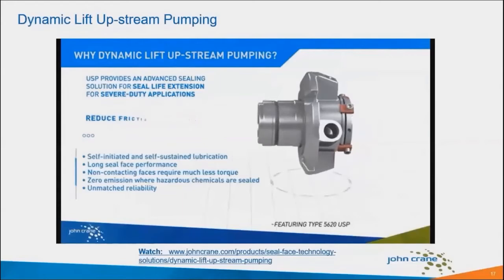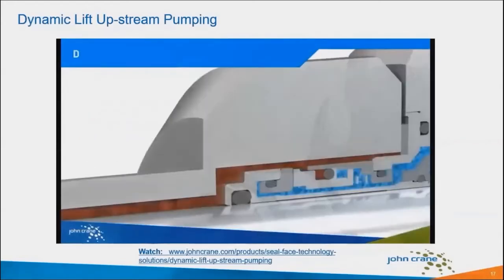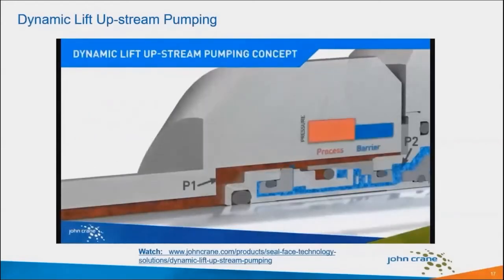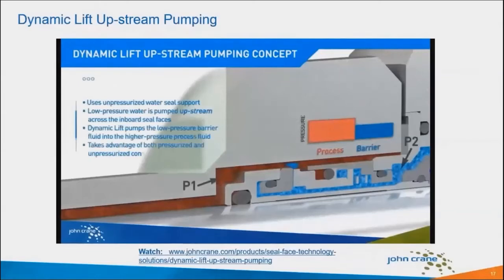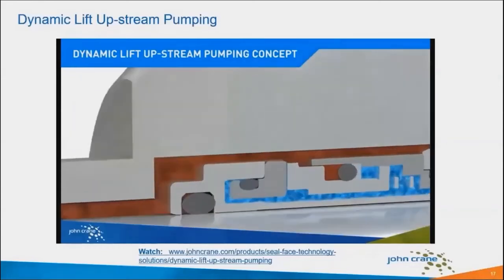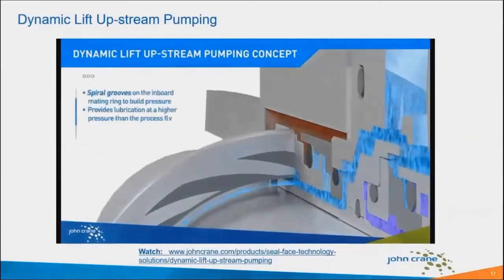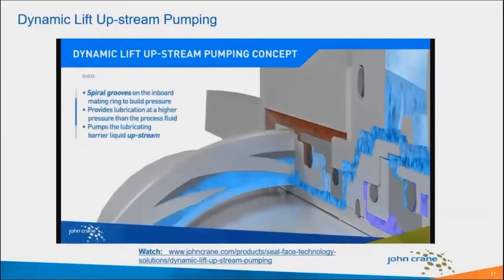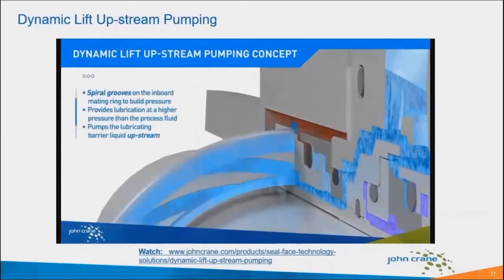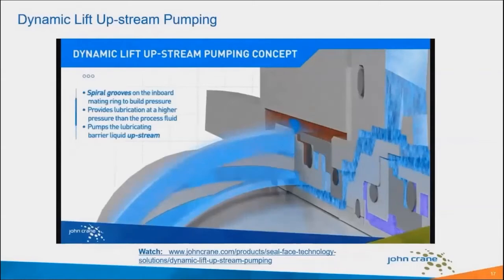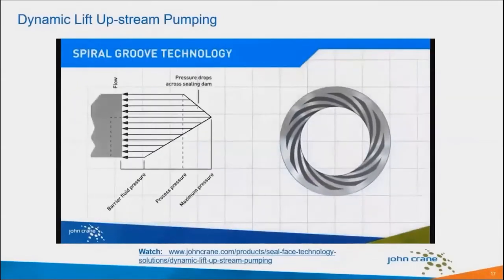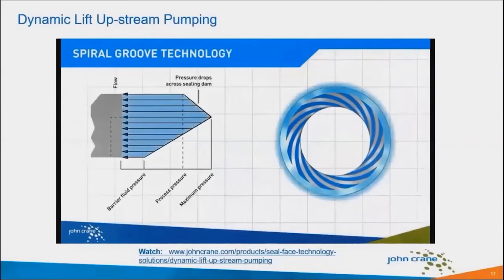So the important thing to keep in mind here, the takeaway, is the water inside the seal is at low pressure, probably about 20 psi. We can see that lower barrier pressure is much lower than the process pressure. In many cases, it's a fraction of the process pressure. But the spiral grooves, you'll see here, take in that water, force that pressure to increase, and create a tiny flow of clean water across the inboard face. So what this does is really address, there's our nonlinear pressure profile.